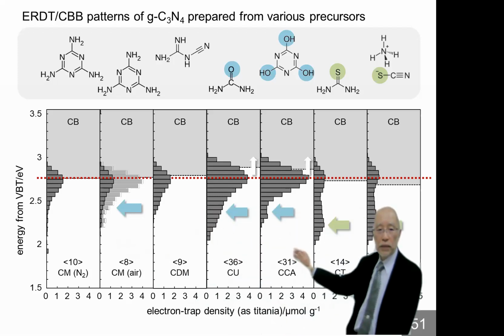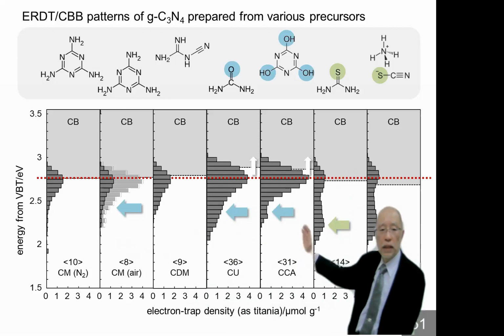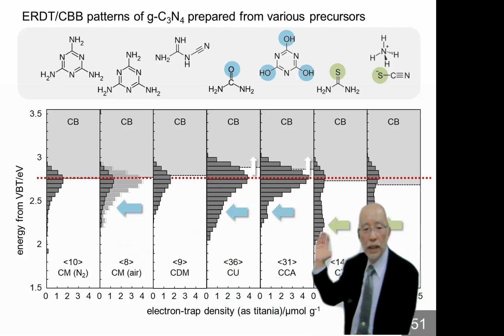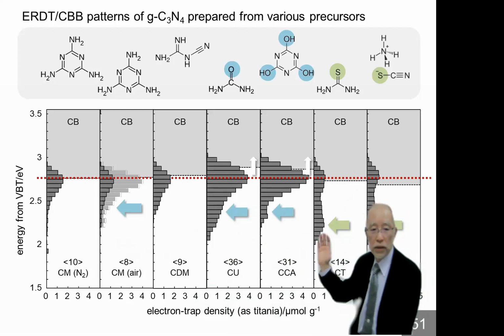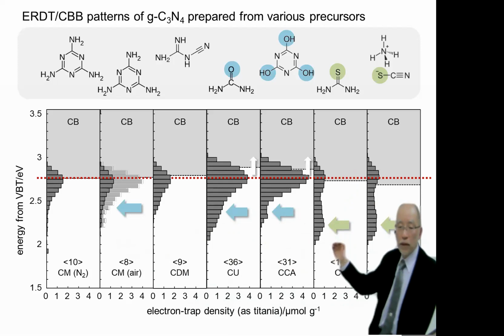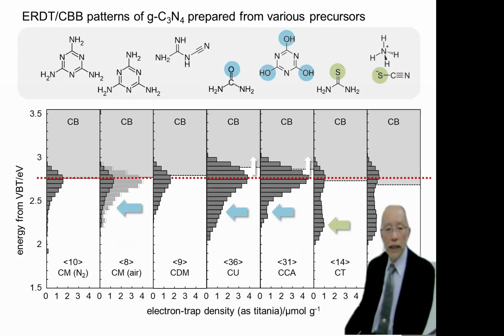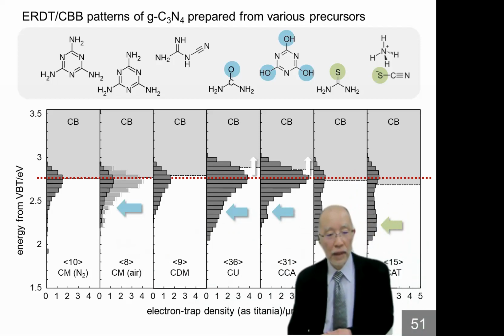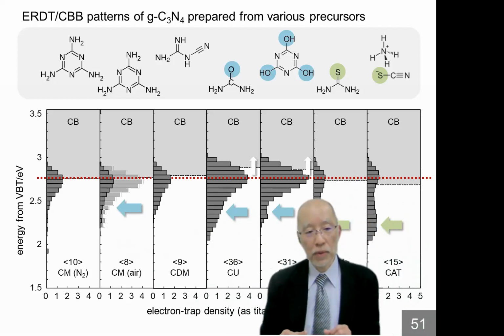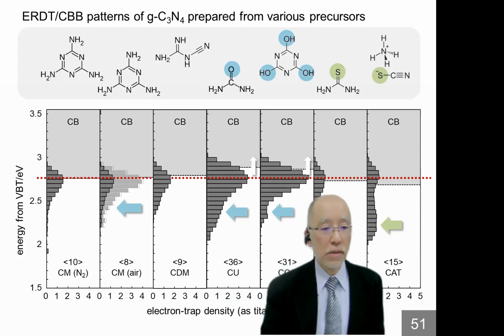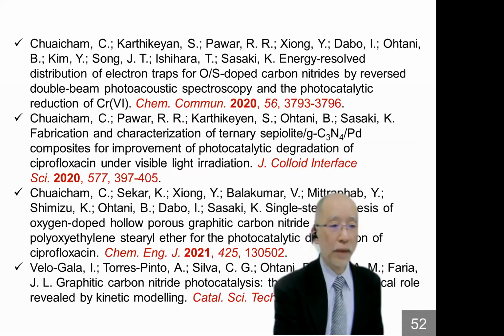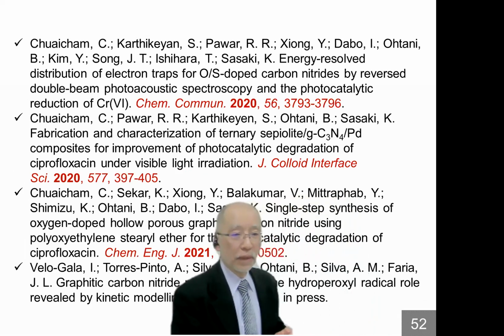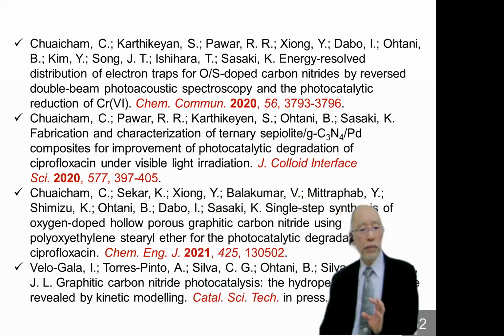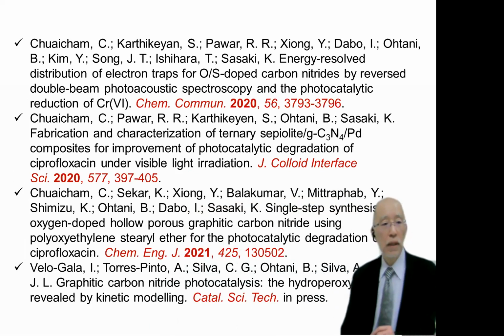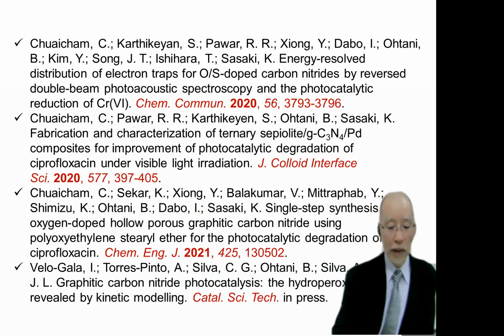And if the precursor contains sulfur, a peak at a still lower energy side appears. And probably this is also reflecting the surface structure containing sulfur. And probably this is the only possible analytical method to characterize those doped carbon nitride materials. And they are very, very active, and already 4 papers have been published using the data of ERDT/CBB patterns for characterization.